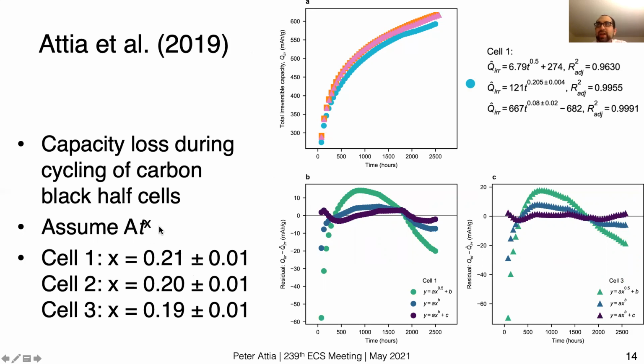We look at the models, the ones with the 3 terms were quite strange, but exponents here are very low, 0.2-ish for all of them. These are 3 triplicate cells, and for all of them, we can see, again, the pretty clear systematic trend in the residuals. So same story here, but very far from 0.5.